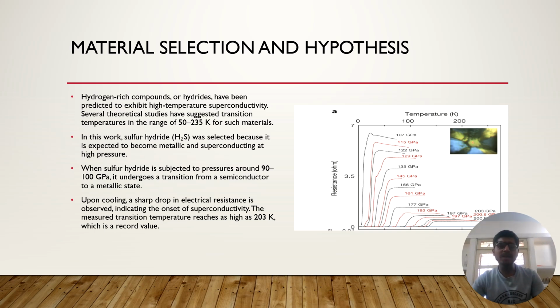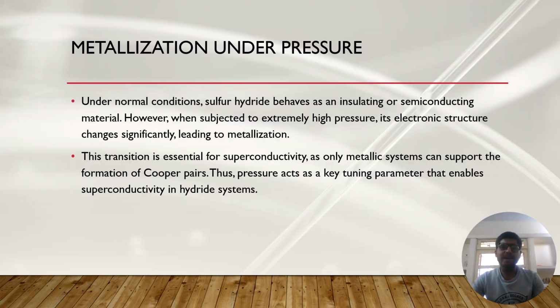But for this to happen, metallization is essential. At normal conditions, sulfur hydride behaves as an insulator or semiconductor due to the presence of an energy band gap between the valence and conduction bands. However, when high pressure is applied, the interatomic distance decreases significantly. This leads to stronger overlapping between electronic orbitals. As a result, the energy bands broaden and the band gap gradually reduces. At sufficiently high pressure, the band gap closes completely and the material undergoes a transition to a metallic state.